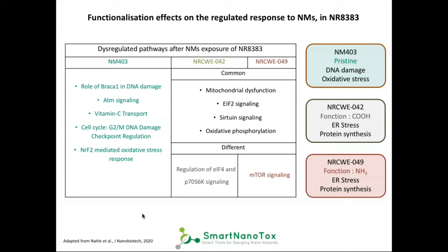On the contrary, the functionalization shows some common pathways activated for both amine and carboxyl carbon nanotubes. Again, it is mainly response to oxidative stress, inflammatory response, or ER stress. So we have the defense response of the cells.